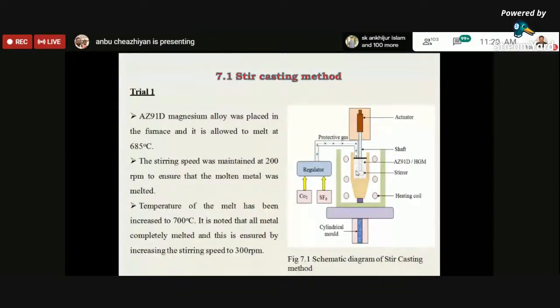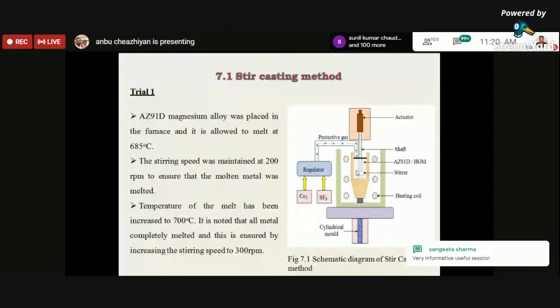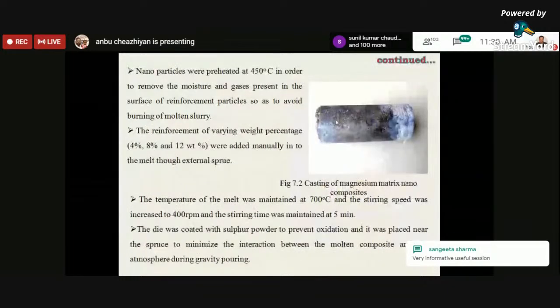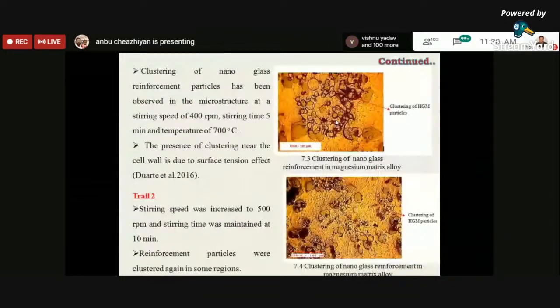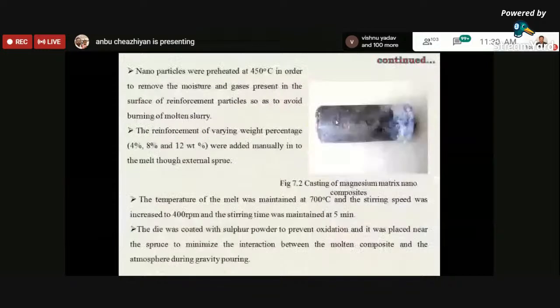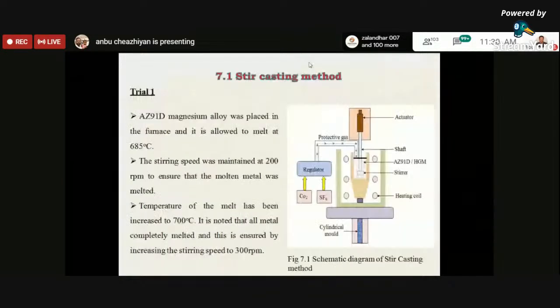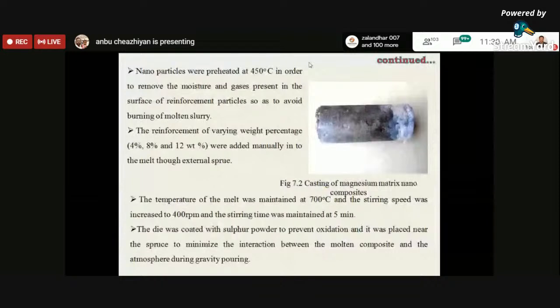Then we increased the temperature to 700 degrees centigrade, and the stirring speed was increased to 300 rpm. The nanoparticles are preheated at 450 degrees centigrade in order to remove the moisture and gases present on the surface of the reinforcement particles.